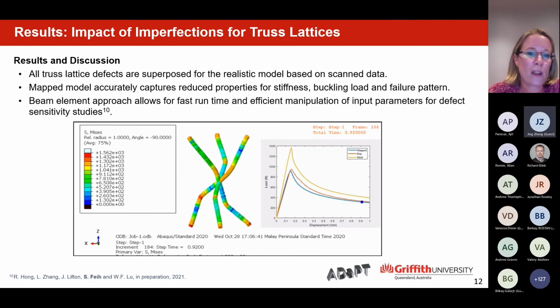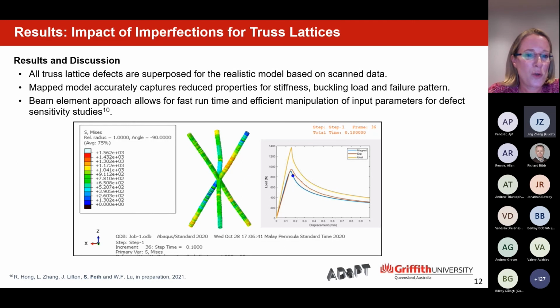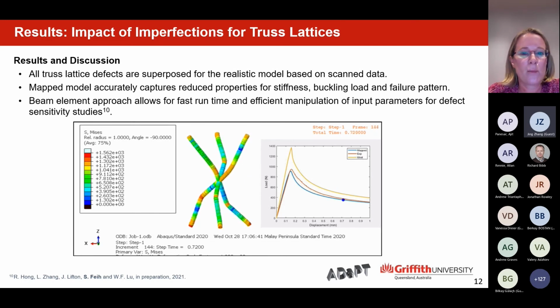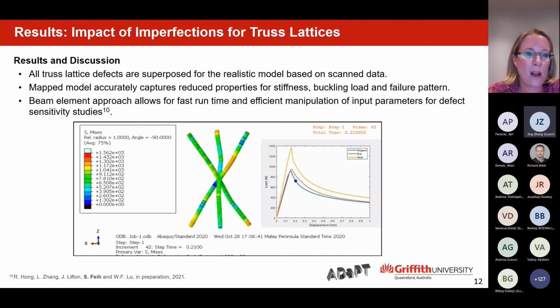Very importantly, the yellow line would be the ideal, the red line is the experiment, the blue is now the simulation. And we can see that the agreement is much better. The stiffness has reduced, the peak stress has reduced. So we can systematically study the input parameters for defect sensitivity studies here with this beam element approach.